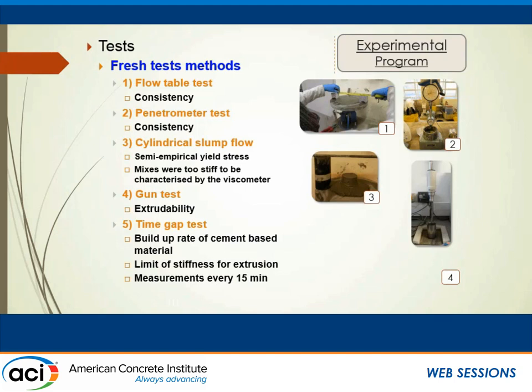To measure the samples, we measured the workability and consistency using a flow table, and we used penetration, and we'll show later on how it correlates well with the fresh properties, with slump flow. And we also try to empirically evaluate the value of the yield stress using the cylindrical measurement.